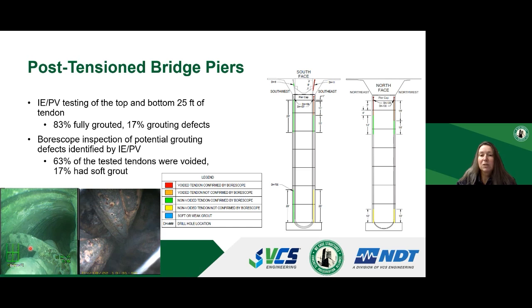Yellow color indicates also fully grouted tendons according to impact echo, but they were not confirmed by borescope inspection. Red color indicates a void that was confirmed by borescope inspection, and orange is a void in impact echo, but not confirmed with a borescope. In addition, when we make a borescope opening and there is grout present, the technician probes the grout with a screwdriver to determine if the grout in the duct is a hard, high-quality grout, or if it's a soft grout that creates a corrosive environment for the tendon.